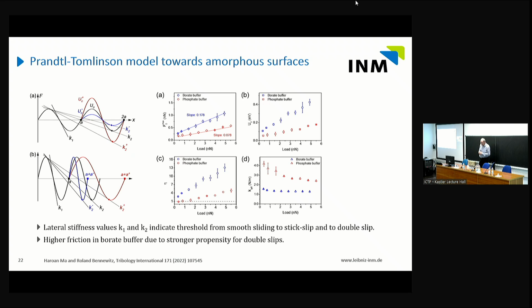And here you see essentially 4 graphs, where A is something like the maximum force as a function of load for the 2 different solvers, then the calculated maximum height of the potential energy surface, and then this eta parameter. So you remember that if eta is smaller than 1, you would have a smooth sliding. If eta is larger than 1, you get stick slip, because essentially the height of the energy potential is larger than the elastic energy stored in one slip, in one sticking phase, essentially.